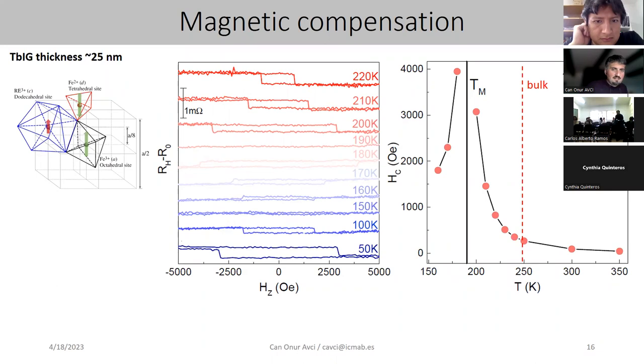Yeah, I think in this 150K, it's just not visible here. The jump, but when the sublattice magnetization changes sign, you have a flip of the anomalous Hall effect signal. But on the background, there's a continuous temperature dependence of the anomalous Hall effect. So it seems like you have a double sign change, but only one of them could be associated with the magnetic compensation, because that's where you see this divergence of the data, if you want to quantify your magnetic compensation, and not the sign of the anomalous Hall effect in this system.